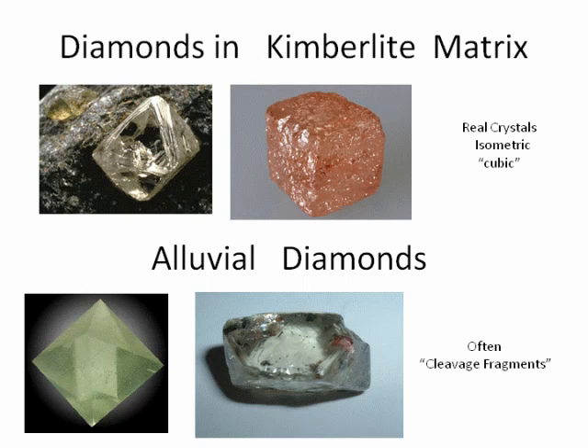The second way, which we often see in the alluvial diamonds, is as they bang into each other, they split along weak bonds. That flat break is called a cleavage. And so I can get cleavage fragments of diamonds. There's a cleavage right there. And when I make a cleavage fragment of diamonds, it will have what they call octahedral cleavage. It'll have four faces coming to a point here, and then four faces to the point at the bottom. And that's a cleavage fragment of a diamond.